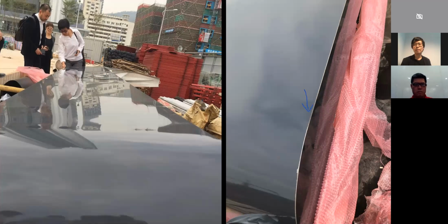So I end up having to live with all this thickness of the aluminum panel, which is silvery in color, which is not exactly what we want. We want something that is completely flat and black. And so that becomes another issue, because coil coating doesn't allow you to assemble the panel first and then spray on it.